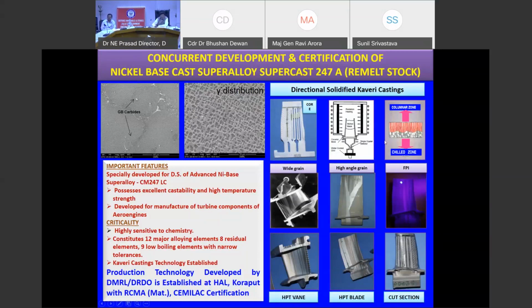And all of them have to come into the grade where you can go right from directionally solidified blade to these are all, each one is one grain. And in that grain, we should have all this phase distribution of particular manner. And then we also have to have some serpentine type of air channels. Only then we can have the aero blade, which will be qualified. So the qualifying of this melt itself will be proven at the blade level, not at the melt level. So that kind of aero qualification comes into picture, and the development which is done in the lab will have to be taken to the industry in the limited series production, then in a mass scale production, then assembly, then the engine testing, which is a long way off.